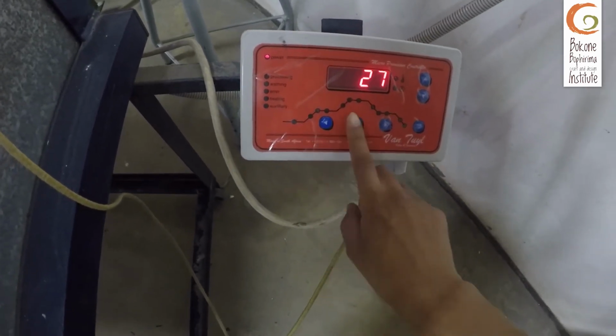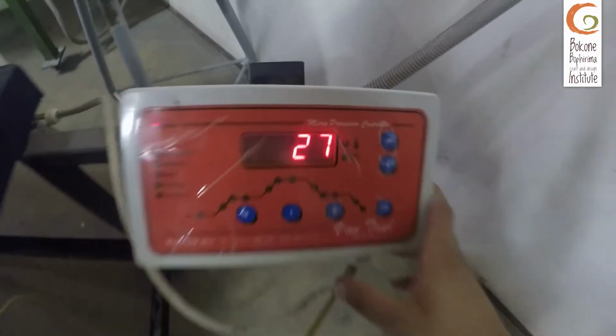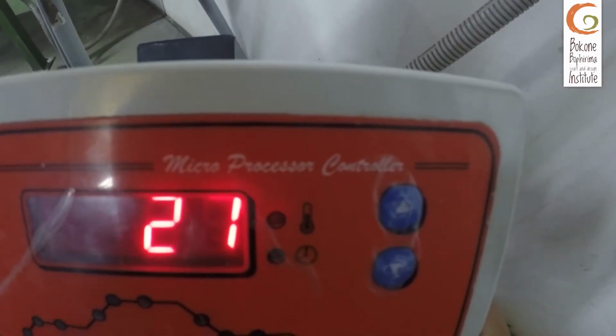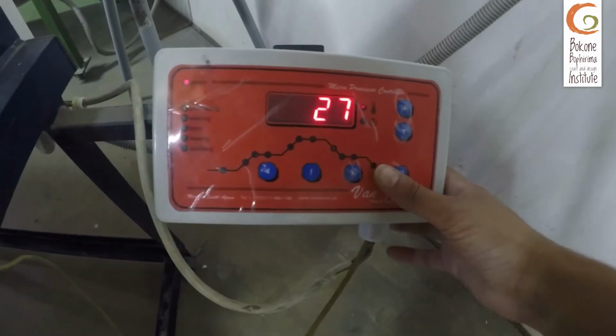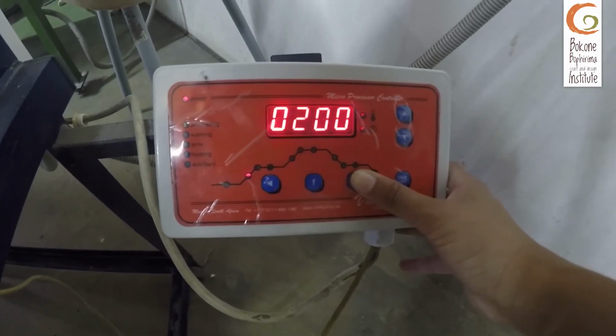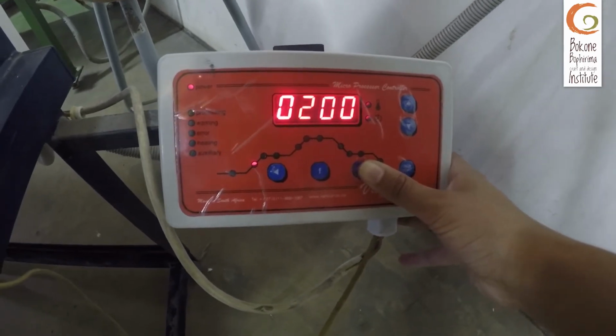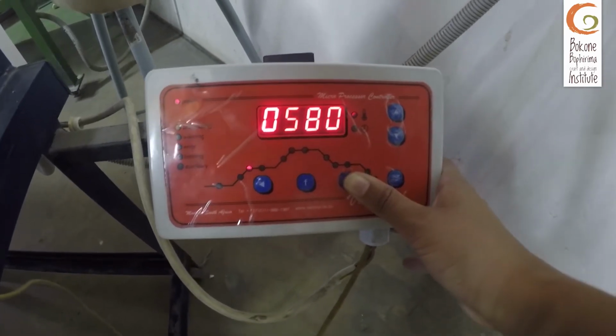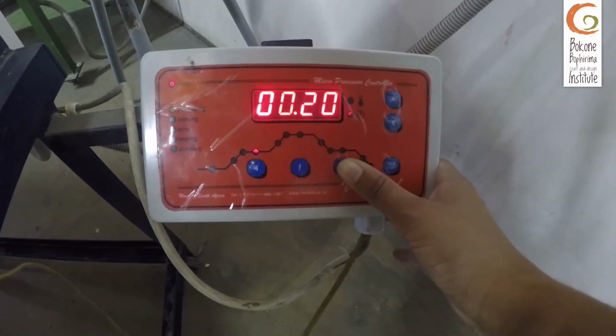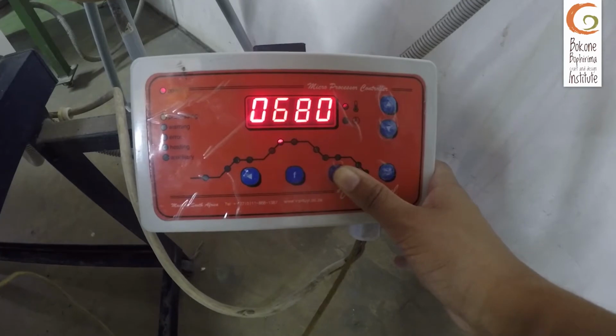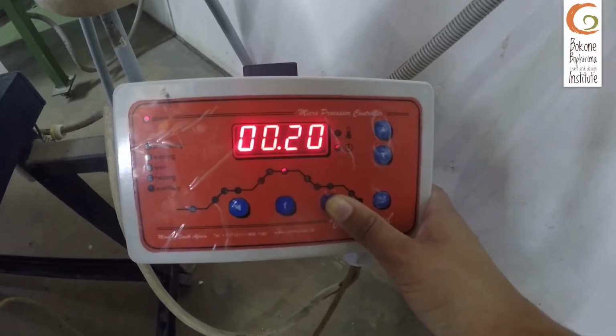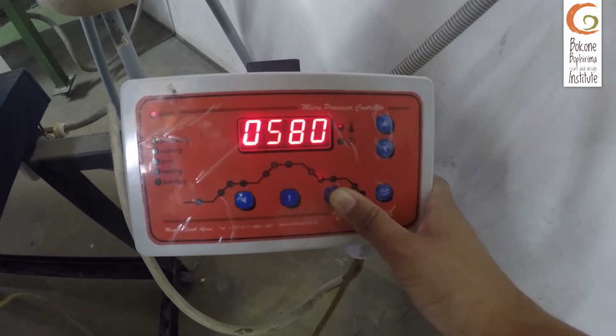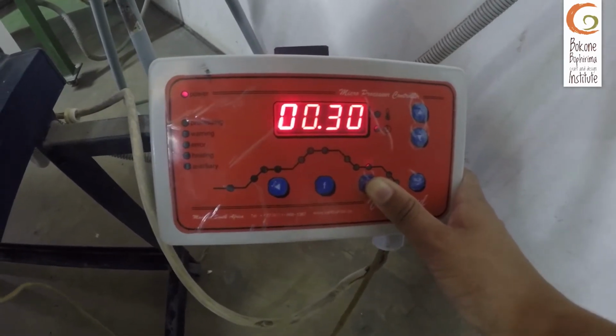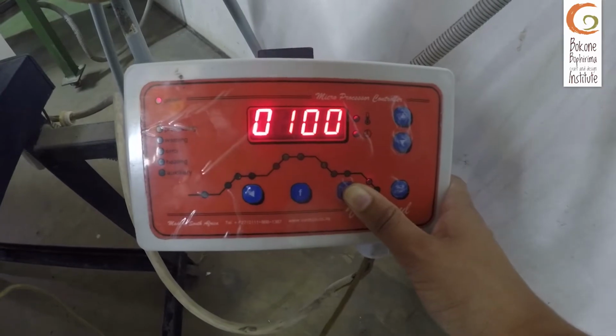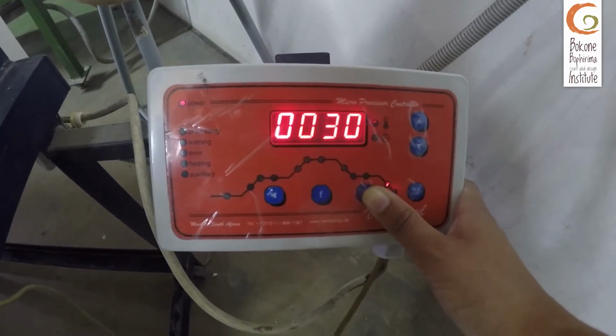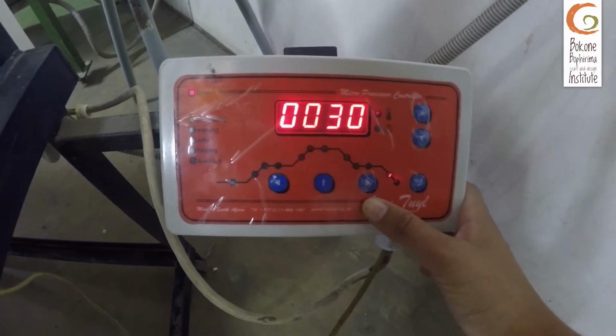And we are starting immediately, going up 200 degrees per hour to 580 degrees, soaking for 20 minutes, going up the ramp at 250 degrees per hour to a top temperature which is 680 degrees, soaking for 20 minutes, coming down full down to 580 degrees, soaking for 30 minutes, then 100 degrees per hour to 30 degrees as our slowing down process.